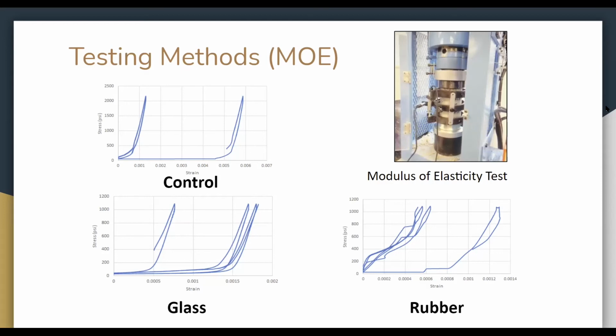For the control sample, the concrete was very stable, and the 3 cycles that can be seen on the left side seem almost identical. For the glass sample, small deviation can be seen in the data of the 3 cycles on the right. And finally, for the rubber sample, measured deviation in the 3 cycles can be observed. This is most likely due to the nature or size of the rubber aggregate that wasn't very compatible with the concrete mix used in this experiment.